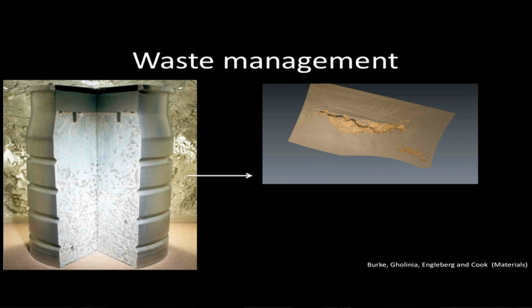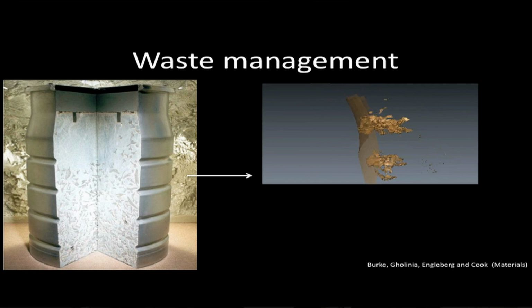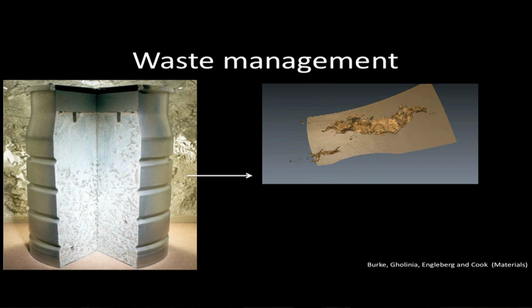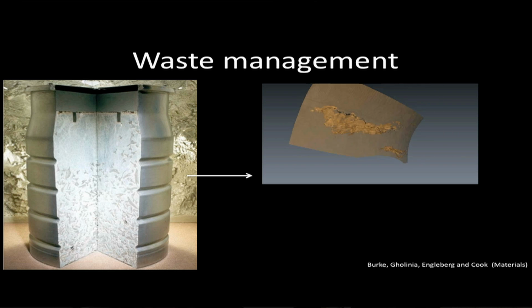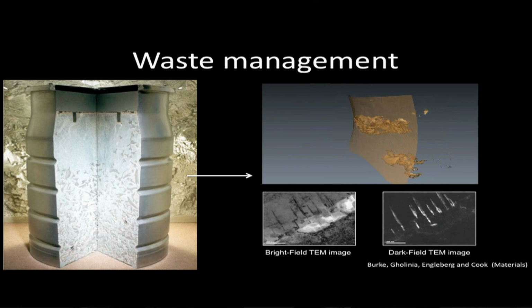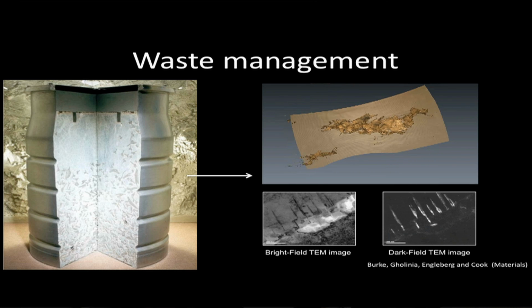And of course, now these days, we like to look at things in 3 dimensions because they give us much more information than just a 2-dimensional plane. But even more than that, we can actually look at the very tips of these cracks, at the microstructure and the chemistry at the tips of these cracks to understand the mechanism by which those cracks grow. Because if we understand the mechanism, we can actually design our materials in a better way so they're resistant to that mechanism by changing the composition a little bit or by changing the microstructure or something like that. So there's a lot of work that goes on in nuclear waste containers as well.